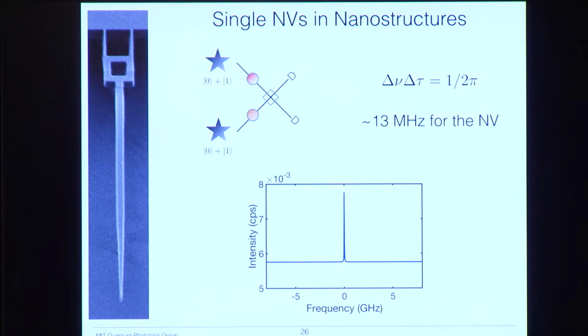So we've done this fabrication in diamond with many NV centers. The structures that I just showed you cannot be used for quantum information processing because it's impossible to isolate just one NV center. So we do this again in diamond with just a few NV centers at the depth that we want, that we make by implantation. And we would like to have NV centers with bulk-like properties in these nanostructures. So what do we mean by that?